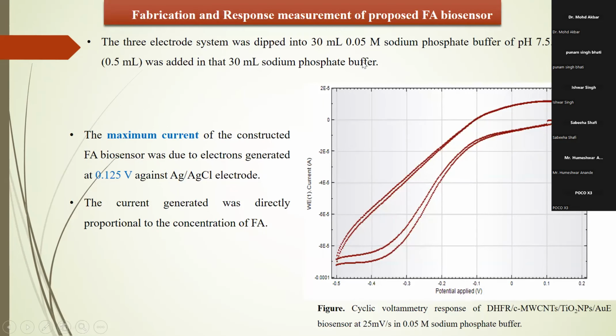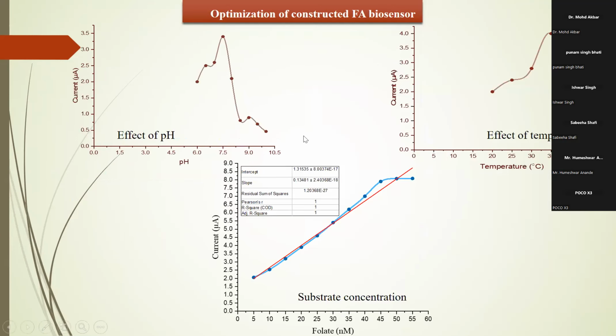Now the response was measured, and it was seen that the maximum current of the constructed folic acid biosensor was obtained at 0.125 volt against the silver and silver chloride electrode that was used as the reference electrode. Now the optimization was also done of the constructed biosensor.